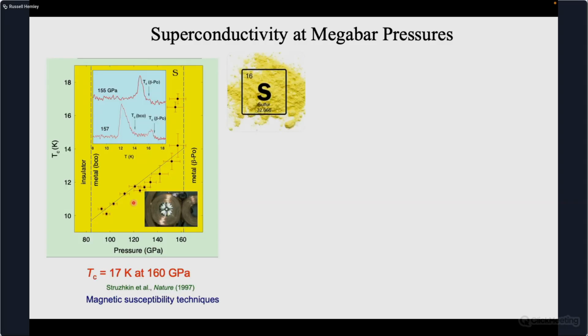So these calculations motivated a lot of work in the 80s and 90s, and we began working on this in the 90s to develop the first techniques for doing studies of superconductivity in the elements, ultimately to look for some of these phenomena in the hydrogen-rich systems, and started with the elements. This was an early study where we used magnetic susceptibility to take sulfur from its insulating state to a metallic state, and found that it becomes superconducting at low temperature in its metallic phase at about 90 to 100 GPa, and it has this increase in TC with increasing pressure. So it has a nice TC of some 17 Kelvin at 160 GPa,